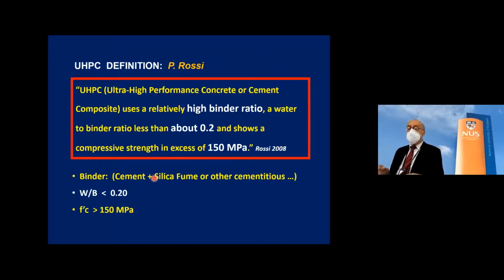The first definition we have, although UHPC existed before 2008, the first definition attempted was given by Dr. Rossi from France in one of his papers. And he wrote the following: UHPC uses a relatively high binder ratio, a water to binder ratio less than about 0.2, and shows a compressive strength in excess of 150 megapascal. Let me explain each one of them.